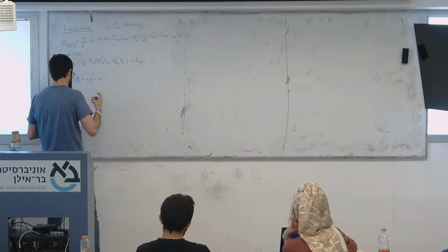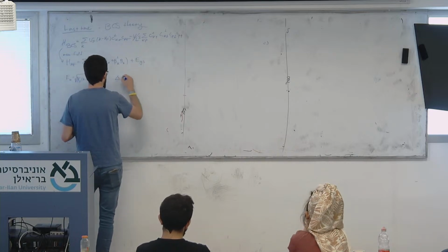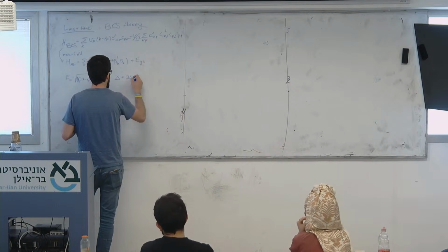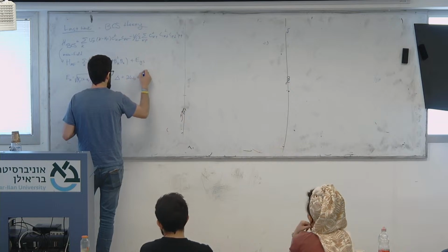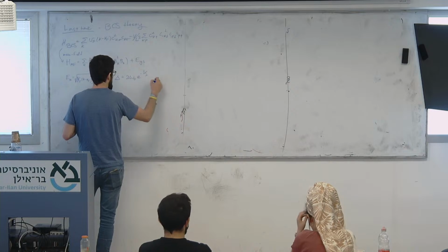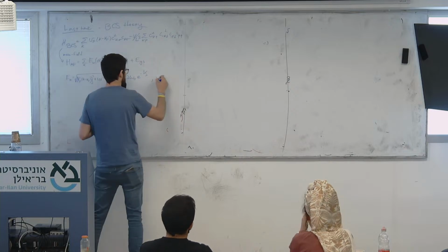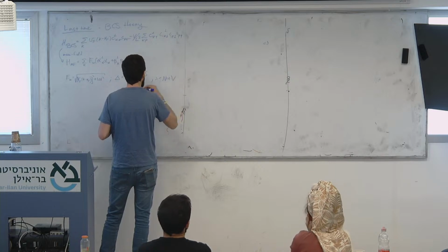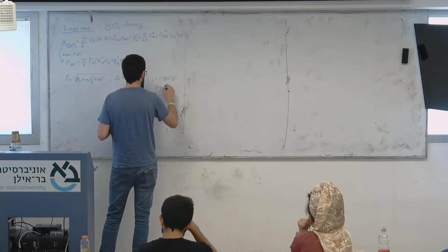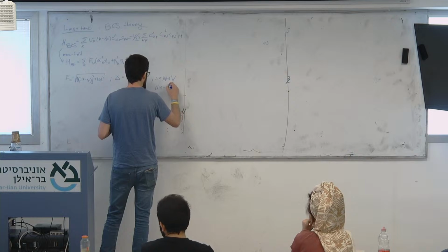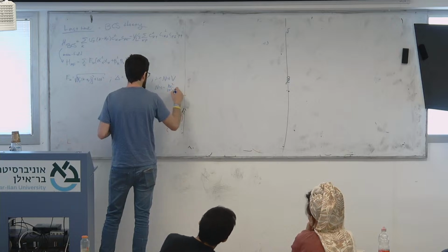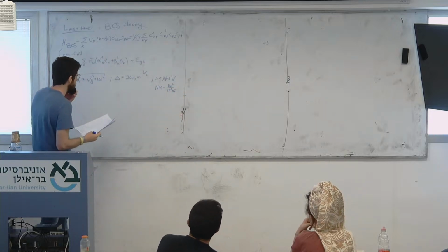We saw that this delta self-consistently is 2 omega D times e to the minus 1 over lambda, where lambda is N of 0 times V, and N of 0 is kF squared divided by 2 pi squared vF in 3 dimensions.